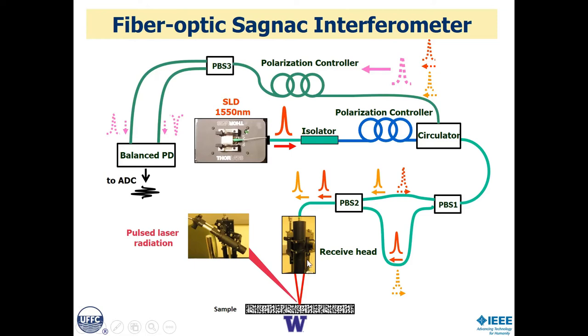What this does is two things. Number one, it makes it very robust because you don't have to stabilize a reference arm. The same optical path is used both for reference and signal. And the second is you get 100% light modulation. So if you have a rough, highly speckling surface, the reference beam and the signal beam have the same speckling, so when they interfere, you have 100% efficiency. So it's very, very robust and very efficient.